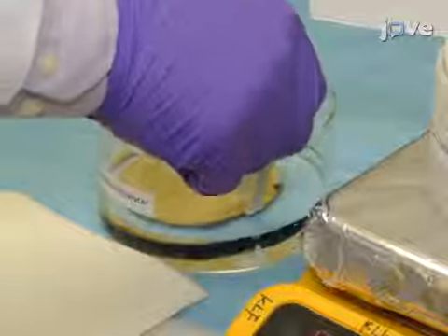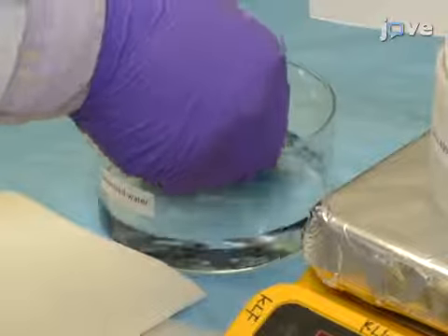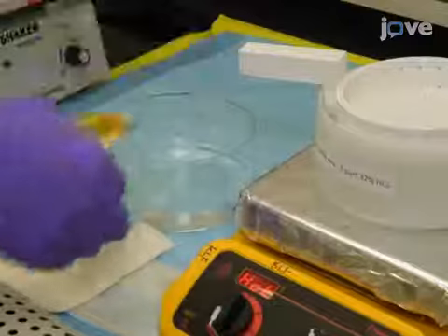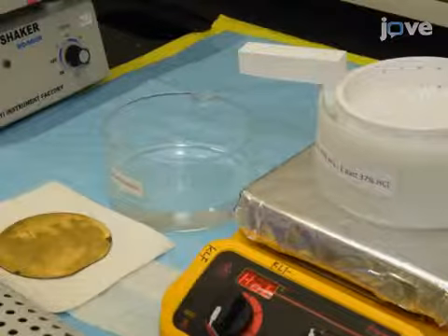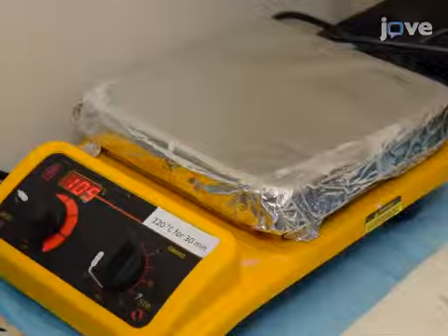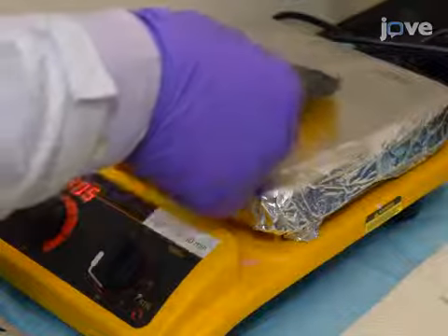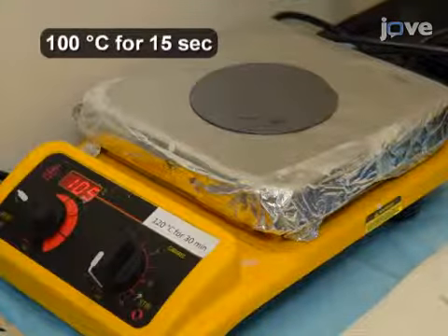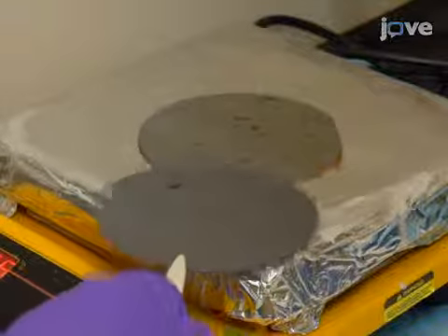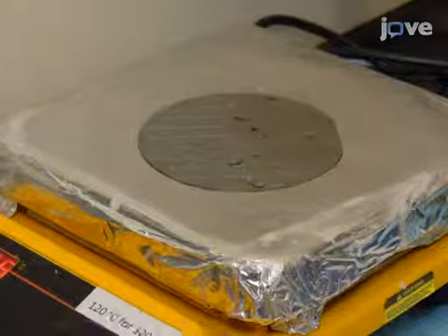When finished, clean the wafer using deionized water and dry it at room temperature. Once dry, place the wafer onto a hot plate preheated to 100 degrees Celsius for 15 seconds. Then, separate the glass wafer from the dummy silicon wafer.